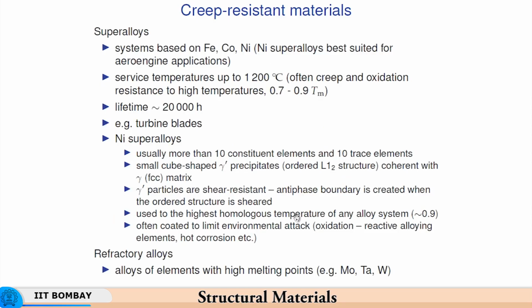When we take superalloys, these are the alloys which are meant to resist high temperatures, and therefore they are supposed to not deform at high temperatures. These are typically alloys based on iron, cobalt, nickel. Inconel 718 is a very popular superalloy. So, Inconel 625, 718, these are alloys involving nickel, cobalt and iron, and these alloys resist deformation at high temperatures. Service temperatures up to 1200 degrees centigrade are possible. Now, these materials also need resistance to oxidation in addition to resistance to creep.